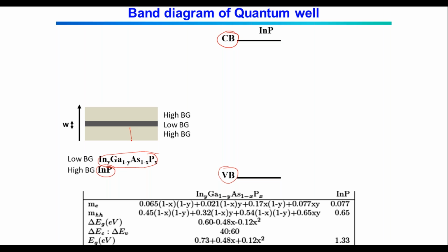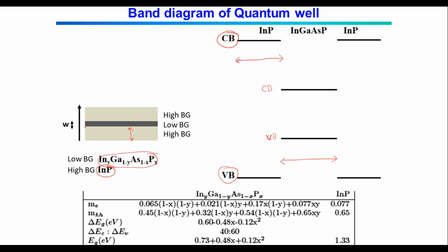So this thickness corresponds to this thickness. Now, once you complete indium phosphide, you are going to have the lower band gap material, which is constructed using indium gallium arsenide phosphide. That has a lower band gap. So the center region is the indium gallium arsenide phosphide, which has a lower band gap. This is the conduction band of indium gallium arsenide phosphide, and this is the valence band. And this thickness is actually this W. So this is W, and then this will be followed by a wider band gap material, indium phosphide. So now I can just draw the energy band diagram for the quantum well structure.